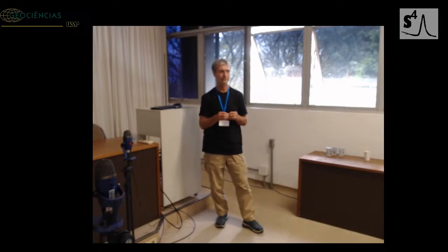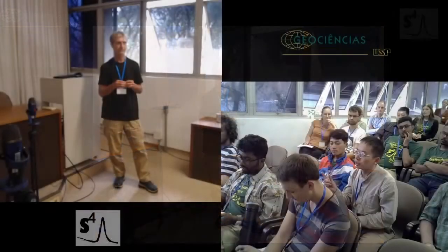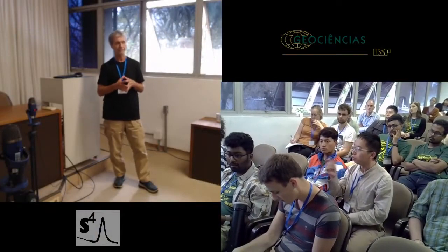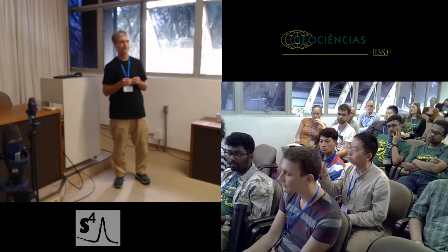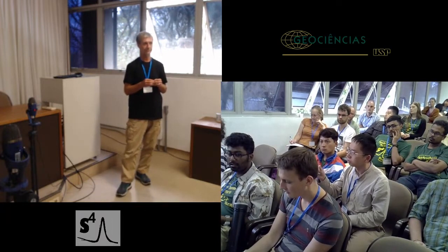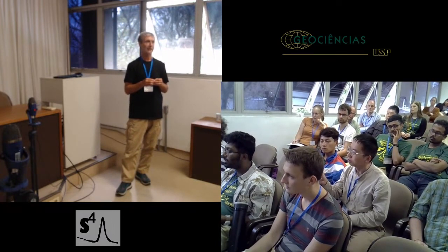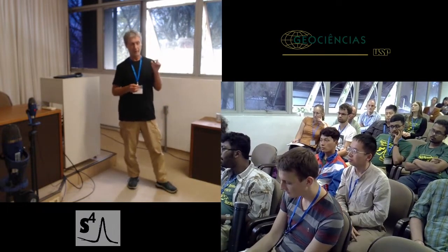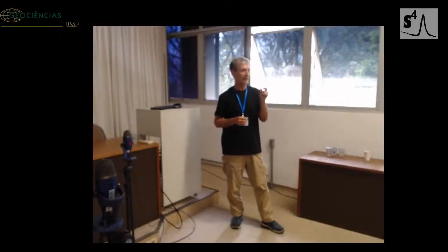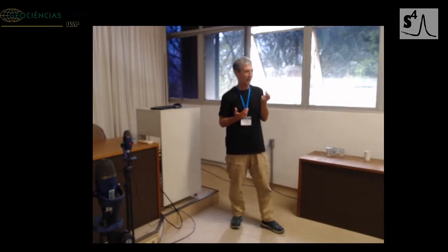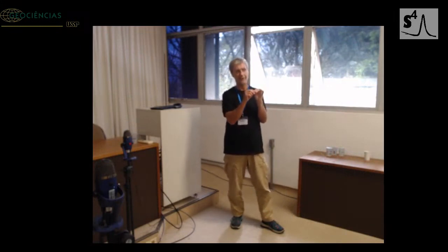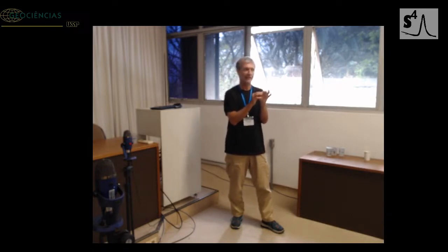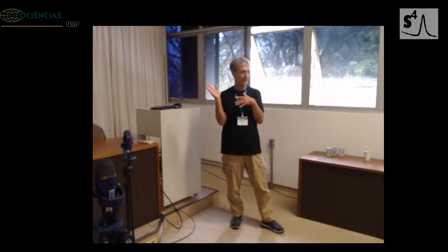Thanks. So, you said ACC is very unstable. Yes. But I read that some people say their speleothem is formed of ACC. So how does it form? Because they sample the very phase that is growing. Amorphous calcium carbonate is unstable, so you do not have any stalagmite made up of amorphous calcium carbonate. You just have tiny crystals. In some cases they are still preserved within the speleothem, but they are very tiny. So unless you use a very high-resolution transmission electron technique, you are not able to distinguish them.